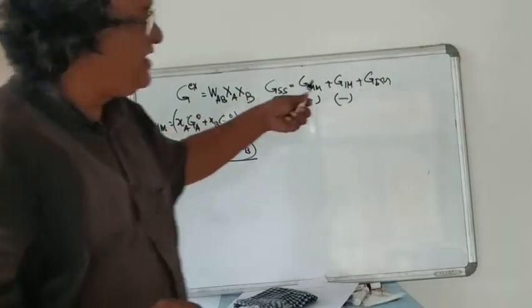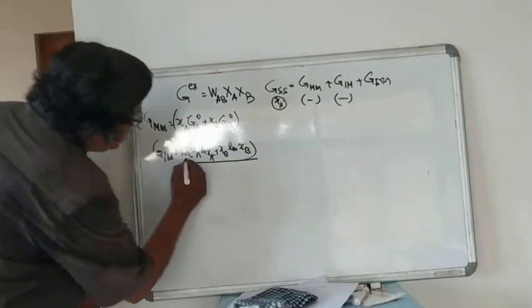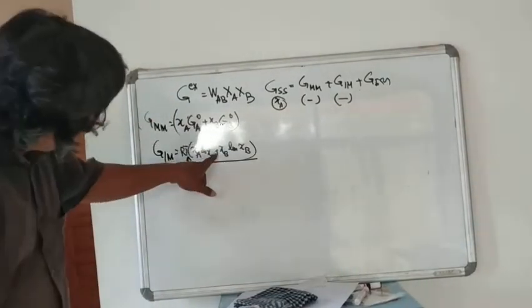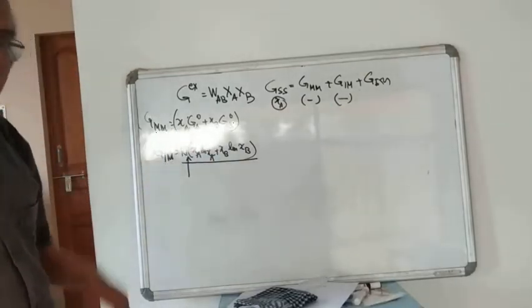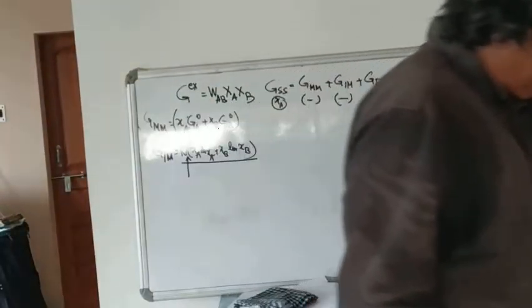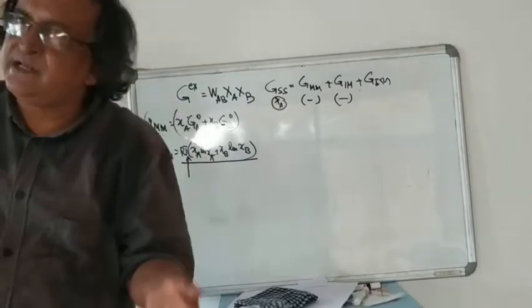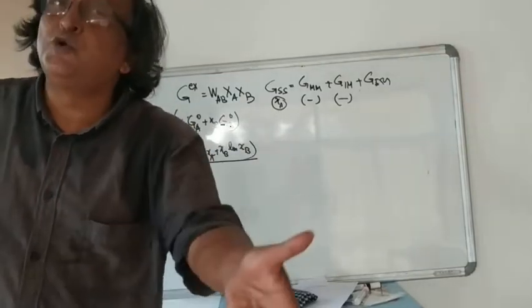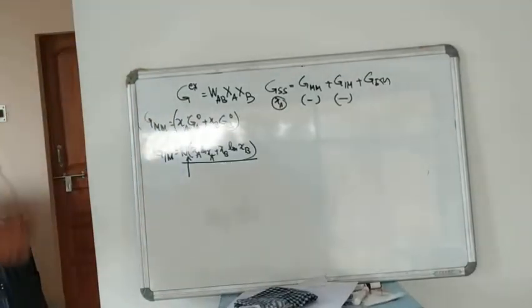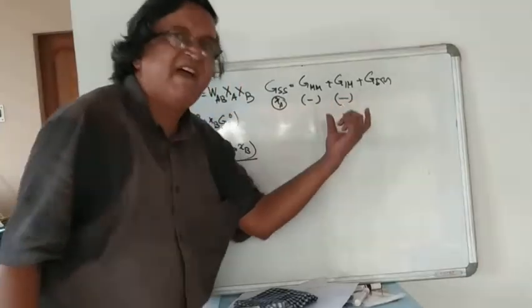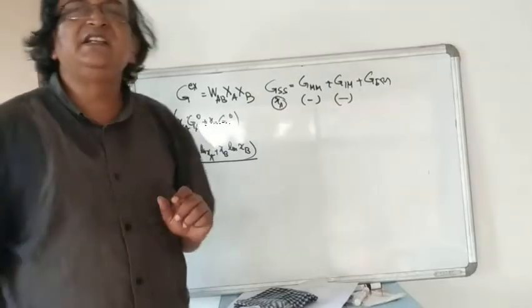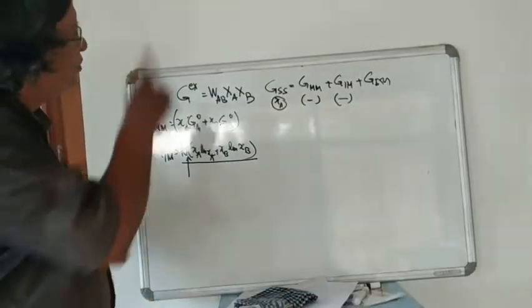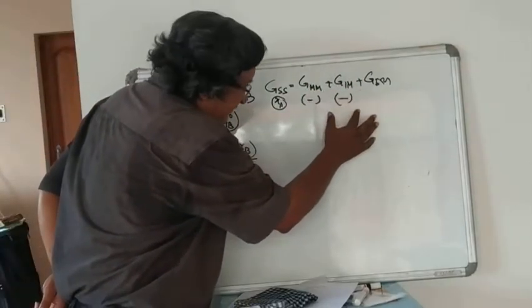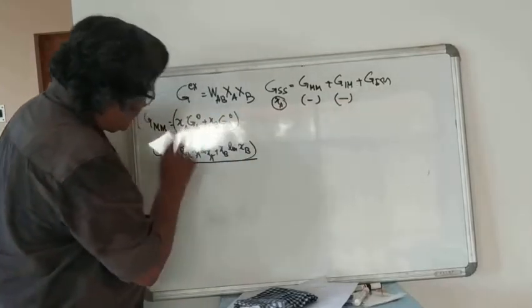The only thing that I want to point out here, and you listen to this very carefully, there is a term T here. So at a particular composition, G ideal mixing will be more negative at higher temperatures. So higher temperature promotes solid solution, because the magnitude of this negative value increases as temperature increases. So, remember this. This term is negative and it becomes more negative at high temperatures.